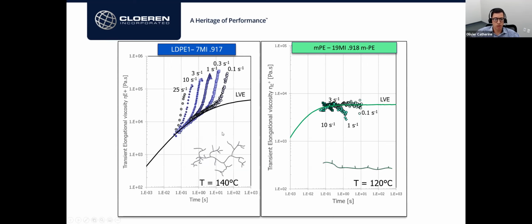We are able to detect or compare behaviors of materials in extensional mode. So for example, here our LDPE1, which has a very highly branched molecular structure, you can see that the transient viscosity at different strain rates is departing very quickly from the LVE, which is the linear viscoelastic envelope, which is basically the Trouton ratio I was mentioning. So the shear viscosity multiplied by 3. And so this is similar to a strain hardening behavior in a tensile test, and really shows the melt strength of the material or the lack thereof.